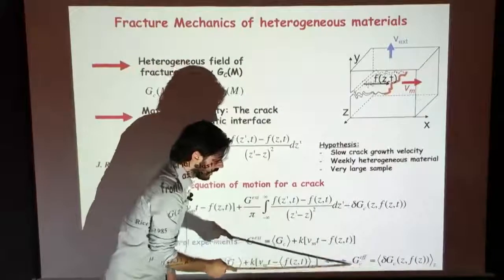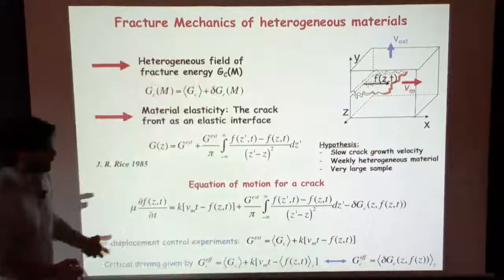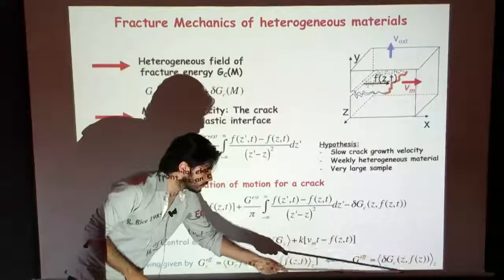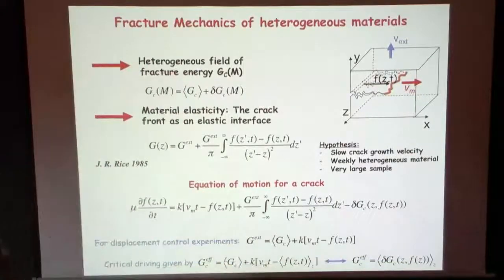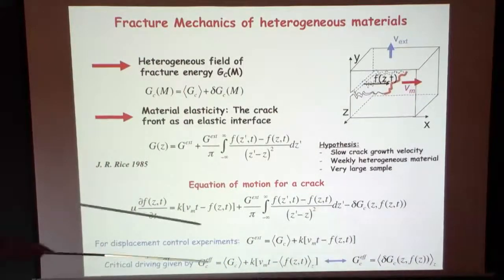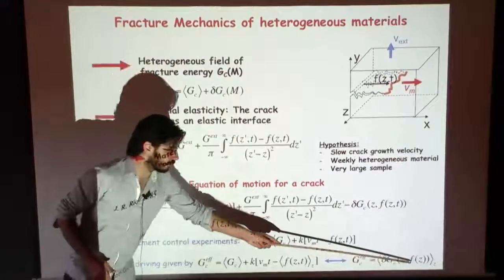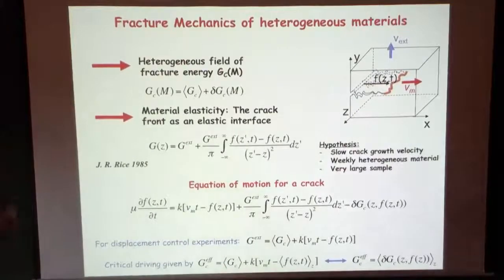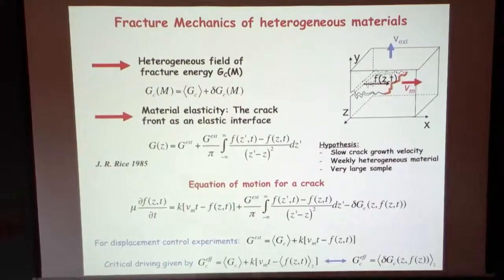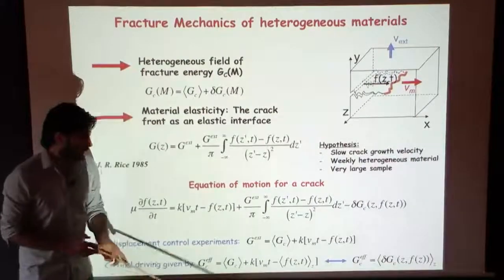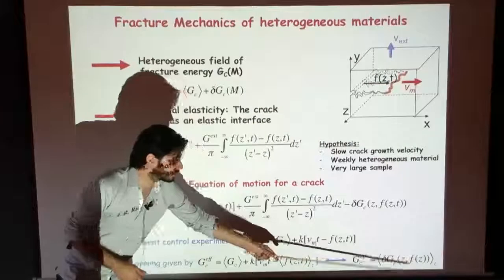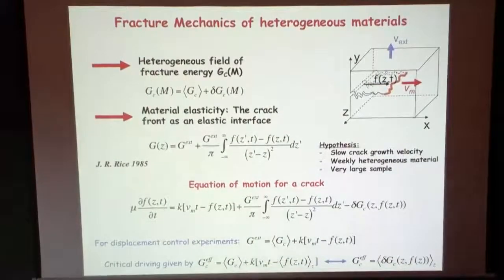If you plug that into that, you realize that the effective resistance of your solid is the average of this term over Z. So my point here is that, yes? You can continue. Yeah, I finish. So my main point here is that the front geometry tells you what is the resistance of your material, simply because the front deforming picks up some local properties that are going to set the macroscopic property. So determining front geometry is key in this problem.